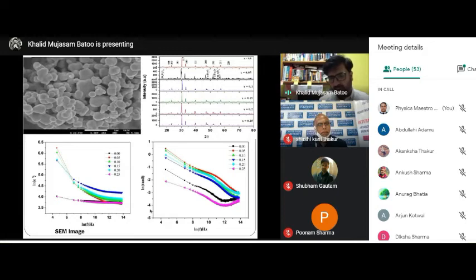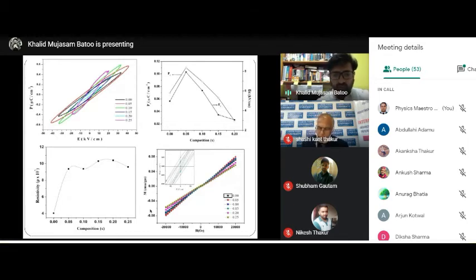We studied the dielectric constant. It was not as high, but it was okay, and the dielectric loss was less. However, when we studied the polarization versus electric field, which is required for a ferroelectric material to be used as RAM, it was not that good. It was very low, and elliptical shaped, not the S-loop shape which we need.